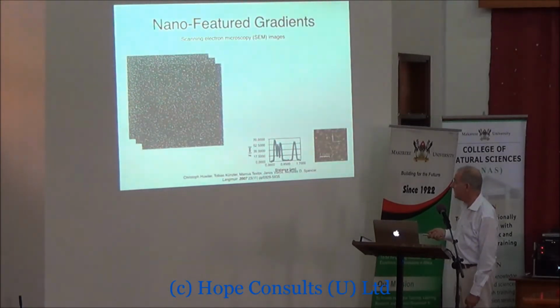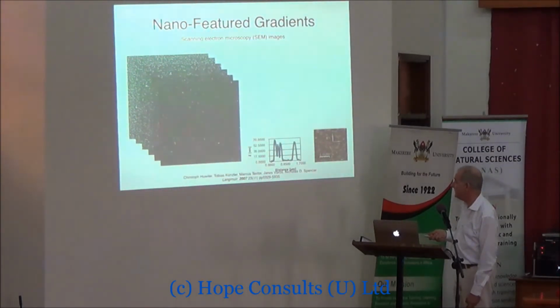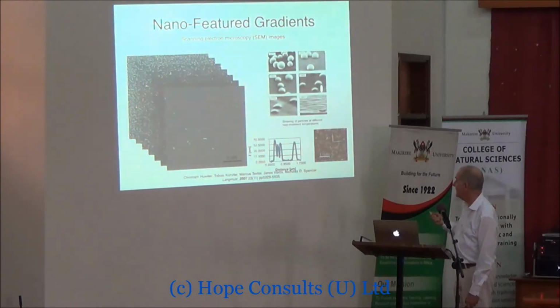This is what it looks like as you go along it with an electron microscope. You can see the change in particle density from one end to the other. This is how they look after they've been sintered into the surface. So this is where we normally stop the sintering, and they're kind of half gone. Here we've gone too far.